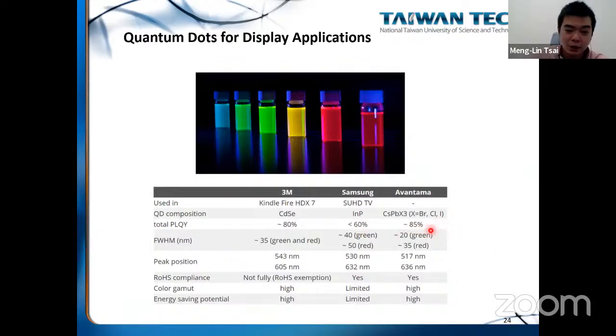You can see the quantum yield is actually higher than the first two, and the emission width is very narrow, down to about 20 nanometers. Even though it has lead, which is toxic, you can see the tolerance for lead is actually higher than for cadmium. So it can pass, but the main problem for this type of material is that it's not stable, compared with the first two.